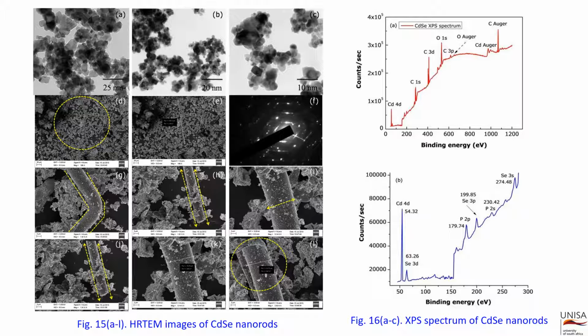it is generally not possible to tell whether different particles are clustered or aggregated without special techniques, which means that though the majority of the cadmium selenide nanoparticles exhibit rod-like morphology, a few particles with spherical shape are also seen in an agglomerated condition in figure 15F. Figure 15F shows the lattice fringes of the nanoparticle corresponding to the 002 and 100 lattice planes of the wurtzite hexagonal structure.